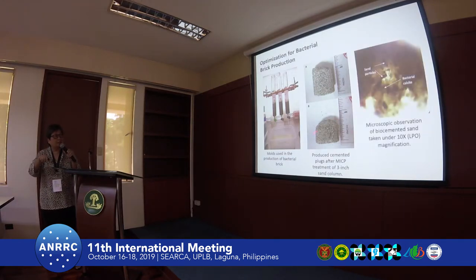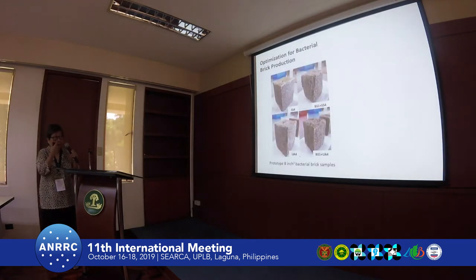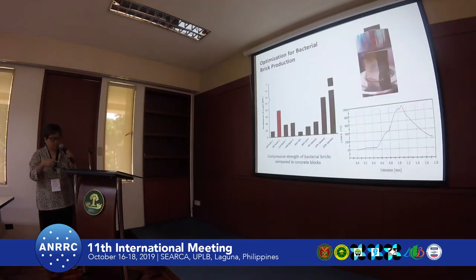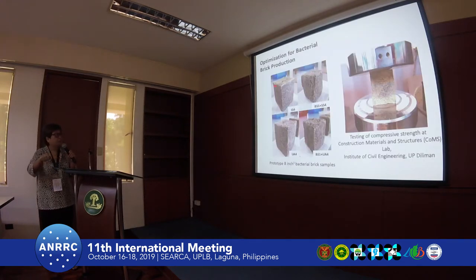But then for our little stubs, when we look at the stubs under the microscope, we saw that these were the sand particles, and they were indeed embedded in the bacterial calcite. So next, we prepared another mold, and then we combined strategies that we read from different literature as well as from our own experience in making the bricks. And we used the isolates SS4 and UA4, and we also included BS1, a mixture of BS1 and SS4. This is because BS1 produces high exopolysaccharide, and we thought that it would provide more nucleation sites for the crystals.